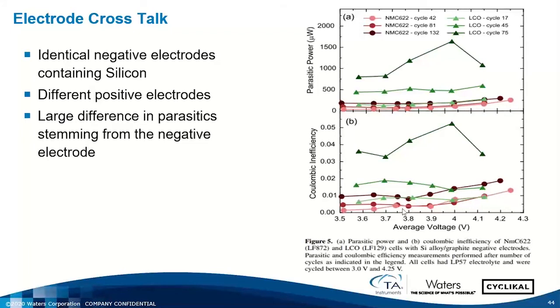And this is all supported by the Coulombic inefficiency measurements. The reason for this is that the NMC electrode is contributing carbon dioxide at the top of charge, and that impacts the overall cycle life of the battery. So an interesting example of how the positive electrode and its contribution to the evolving electrolyte chemistry cannot be ignored.